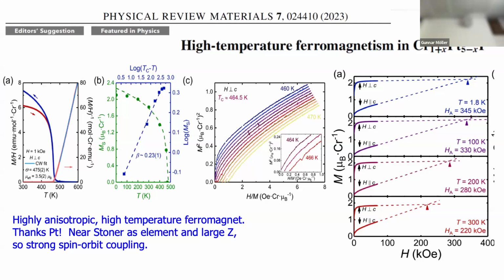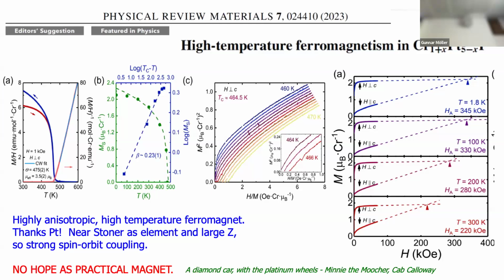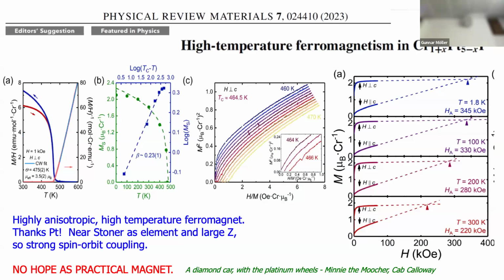Now, this is fantastic because you usually associate this with rare earths or other such things. This is very nice as a demonstration. If you have large spin orbit coupling, you can have large anisotropies in a transition metal like material. Okay, now, on the other hand, before you get too excited, there is, of course, no hope of this being a practical magnet because it's almost all platinum. Now, Cab Calloway sang about a diamond car with platinum wheels in Minnie the Moocher. This is one that would have a platinum magnet. But it's beautiful proof of principle that if you have large Z with transition metals, you have the possibility of getting large magnetic anisotropies, and we might be able to finesse around the need for rare earths.